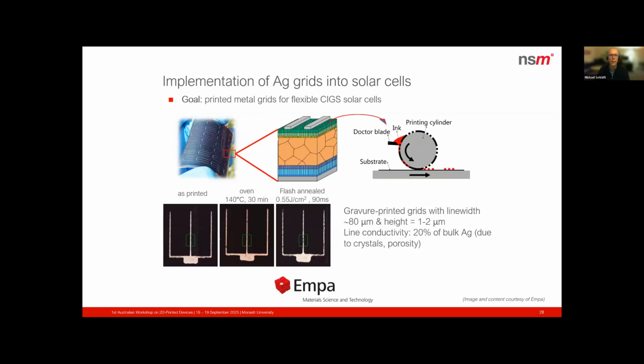As another example from EMPA, here we see work on flexible CIGS solar cells. The grids were gravure printed with a line width of about 80 micron, sorry, 80 micron width, and a height of 1 to 2 microns. After printing, the lines were dried in an oven and then flash annealed to improve conductivity. In the end, the conductivity reached about 20% of bulk silver, limited by crystal structure and porosity.